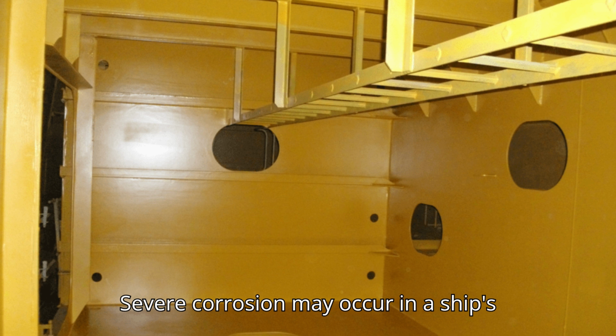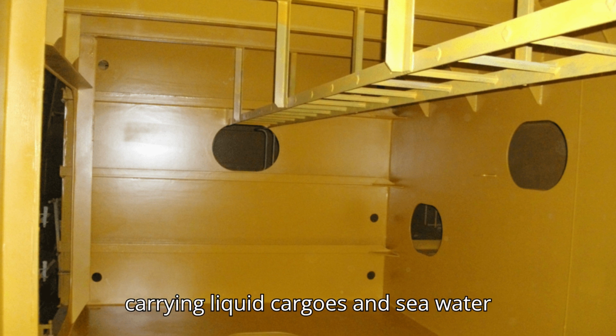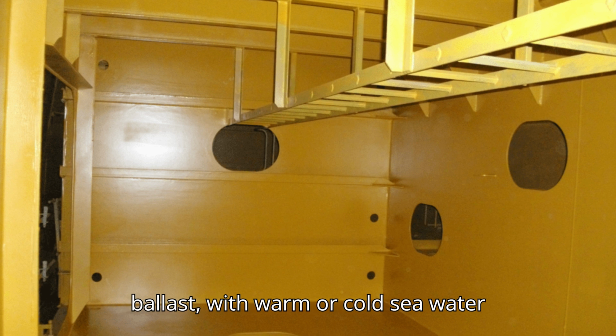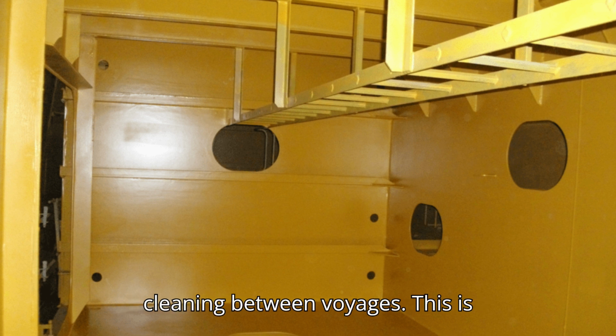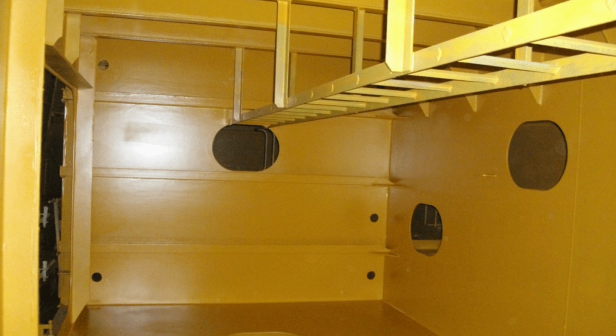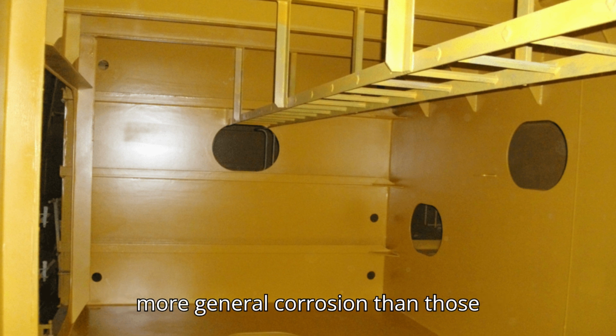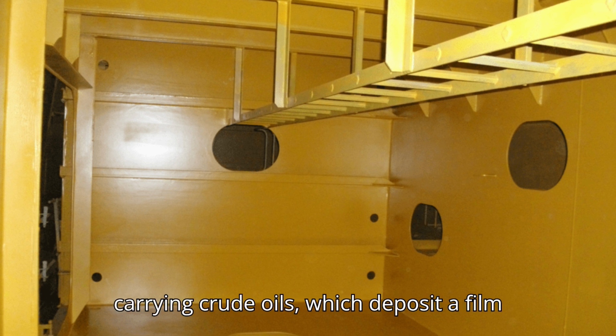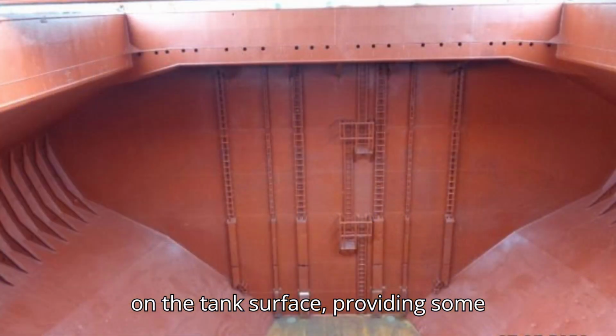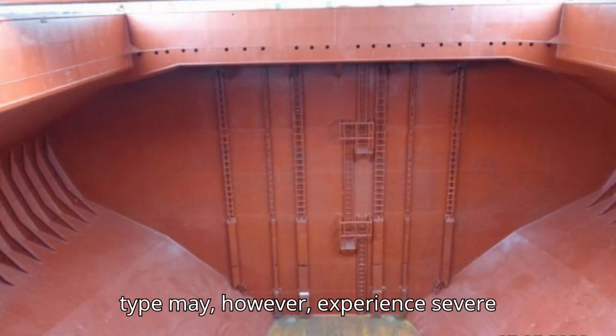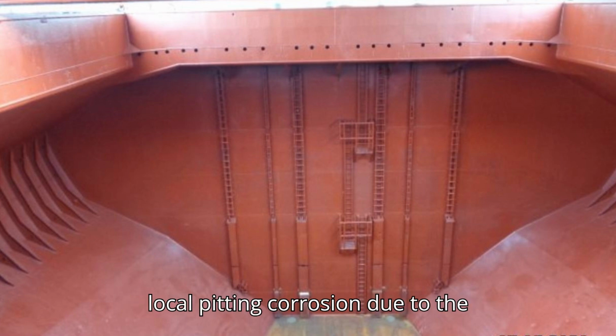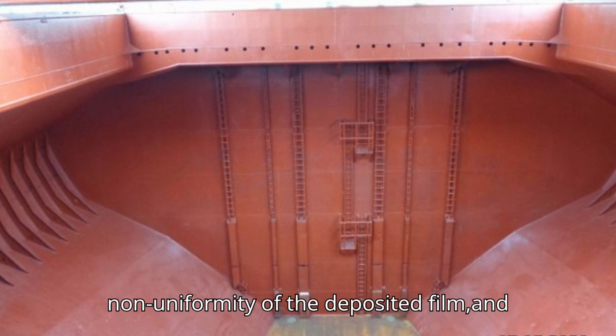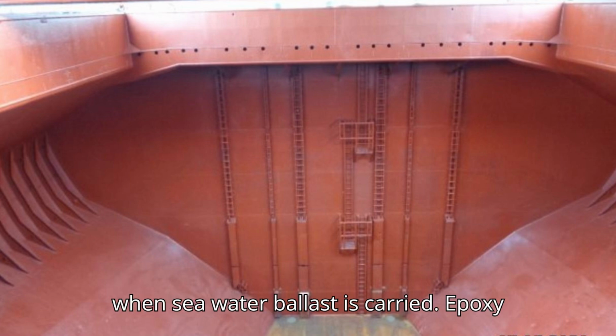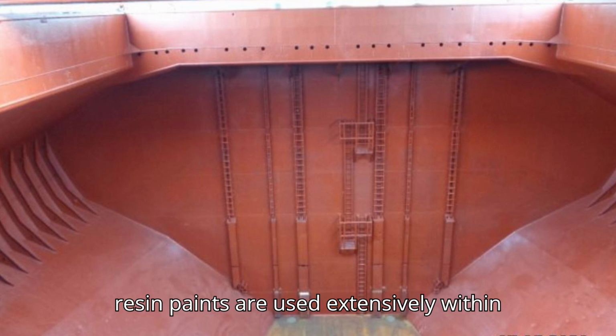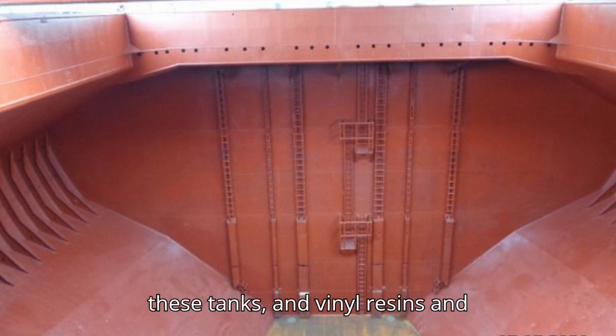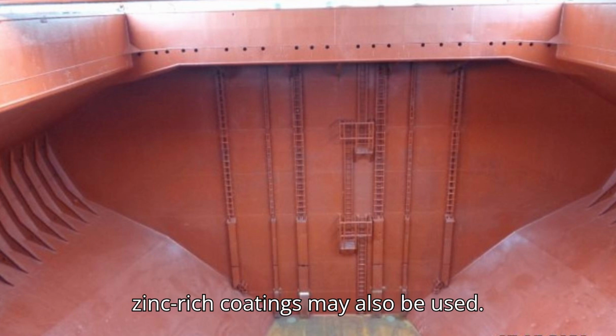Severe corrosion may occur in a ship's cargo tanks as the combined result of carrying liquid cargoes and sea water ballast, with warm or cold sea water cleaning between voyages. This is particularly true of oil tankers. Tankers carrying white oil cargoes suffer more general corrosion than those carrying crude oils, which deposit a film on the tank surface, providing some protection against corrosion. The latter type may, however, experience severe local pitting corrosion due to the non-uniformity of the deposited film and subsequent corrosion of any bare plate when sea water ballast is carried. Epoxy resin paints are used extensively within these tanks, and vinyl resins and zinc-rich coatings may also be used.